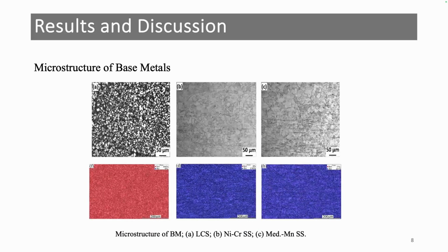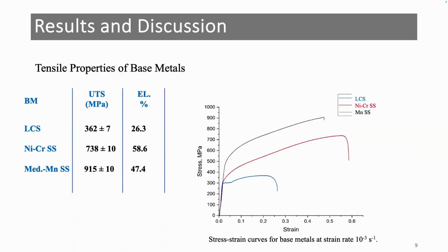For the results and discussion, the low carbon steel has a BCC structure, ferrite and pearlite, and the nickel chrome and medium manganese steels have a fully austenitic structure. This is by optical and EBSD. Regarding the tensile properties of the materials, the low carbon steel here is represented by the blue line, and the medium manganese steel gives higher strength but lower ductility than the 300 series.